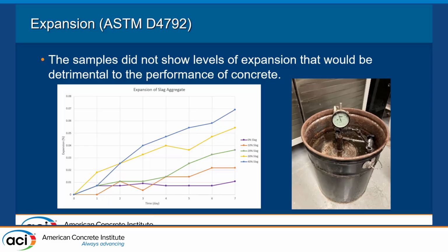On the right, you can see a photo of the final experimental setup with the compacted aggregates under a surcharge weight of 10 pounds, and the dial gauge is how we measured the expansion of the aggregate. These samples were kept submerged in water at 70 degrees Celsius for the week-long duration of the test. And expansion readings were recorded daily at approximately the same time.